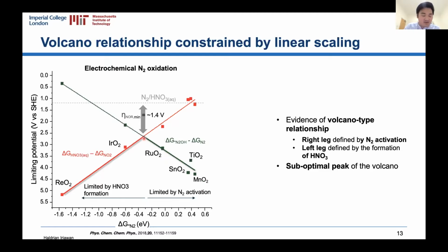However, in contrast, on the left side, the green step, the first step is not as challenging, but the bottleneck step is the product formation. And the optimal catalyst is the intersection of the two, where the two steps are least challenging. However, we see that even at the optimal catalyst, the overpotential, or the bias required, is still very, very large, around 1.4 volts.